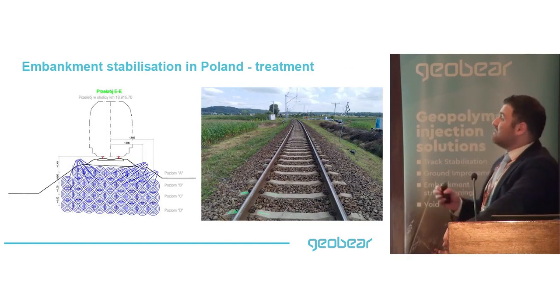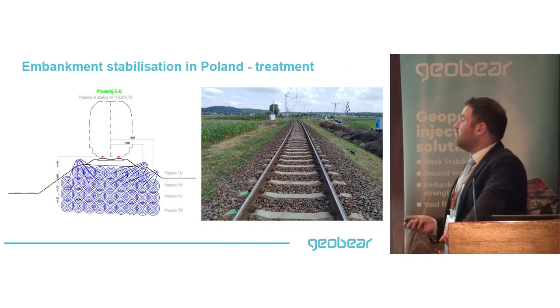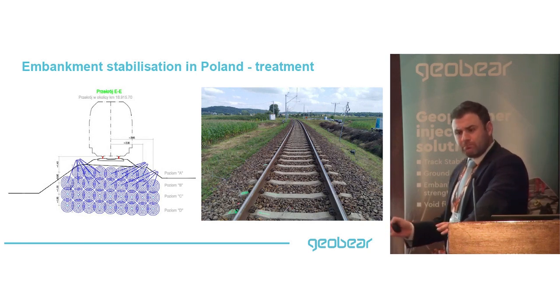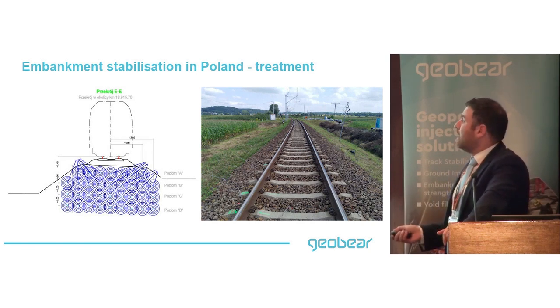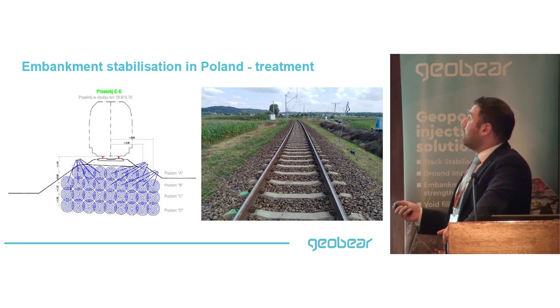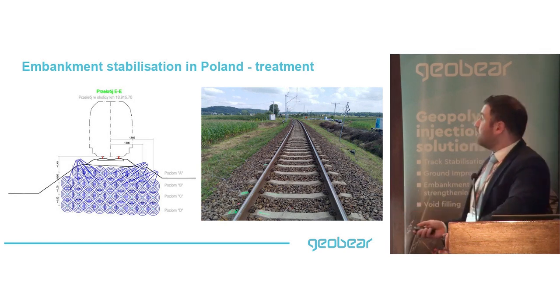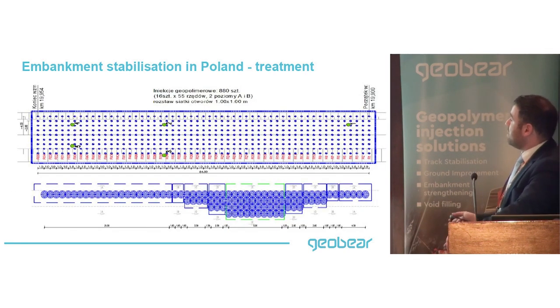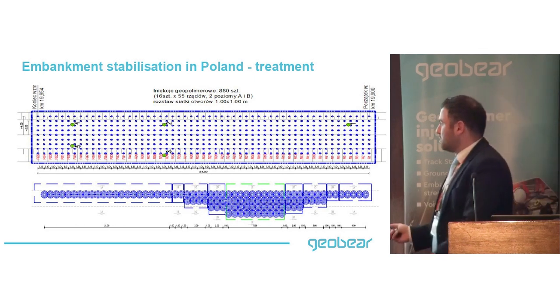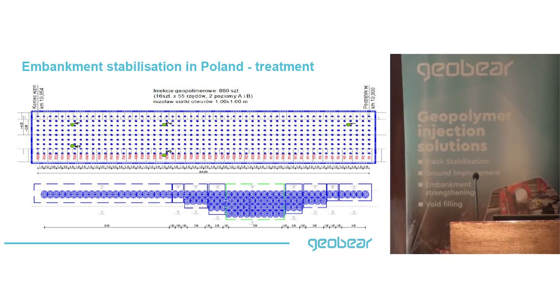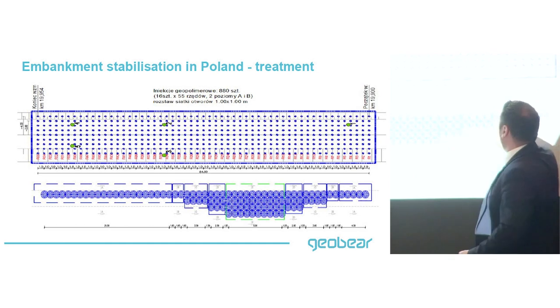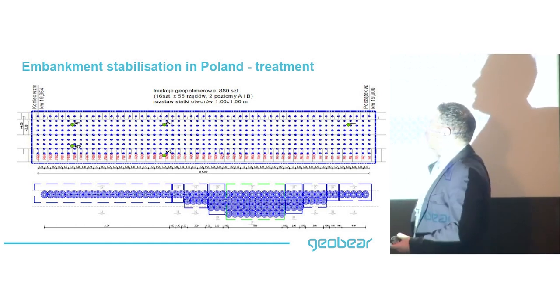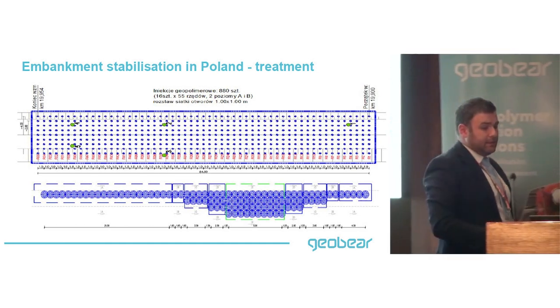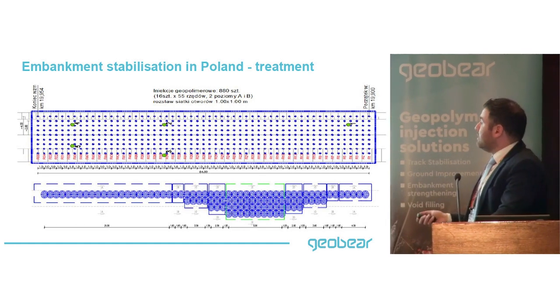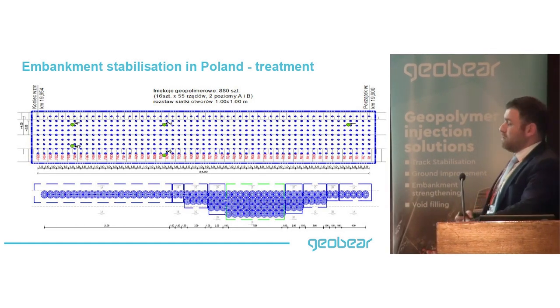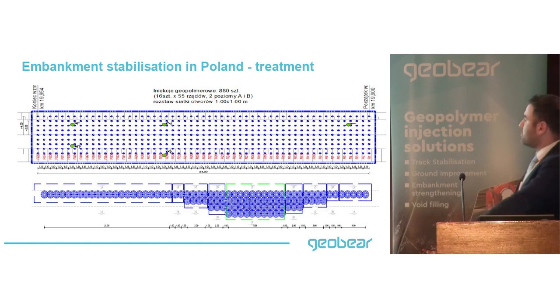We carried out an extensive injection scheme on this one. We treated about 50 meters of track length, injecting at different levels depending on location. We even took into consideration creating a transition zone around the treatment area - the green dashed area shows where the main problems were occurring. We had to create almost like a transition zone in and out of the treatment zone, just to make sure we don't create any track quality faults.